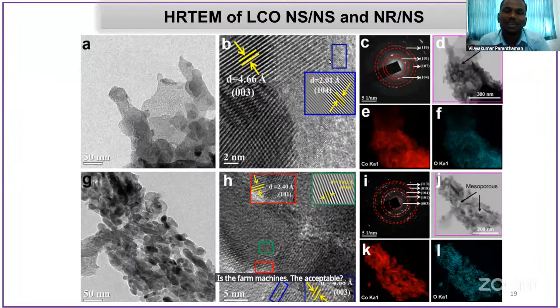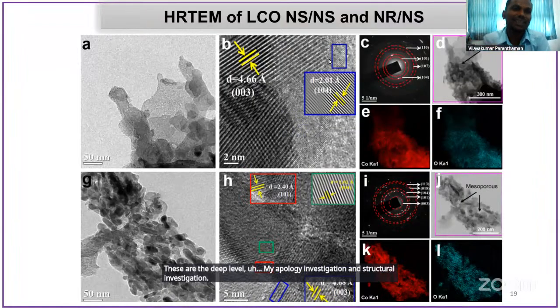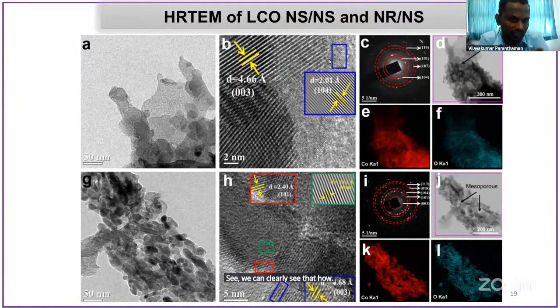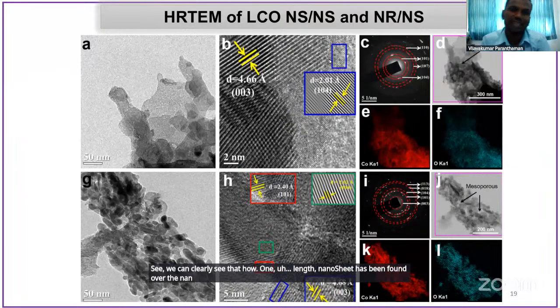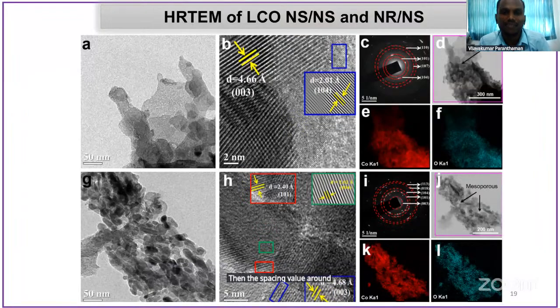These are the deep level morphology investigation and structural investigation. We can clearly see how one-dimensional length nanosheet has been formed over the nanosheet. Small, teeny nanosheets have been formed. Then the d-spacing value is around 4.66 Angstrom. The HKL is 003, in line with the XRD result.